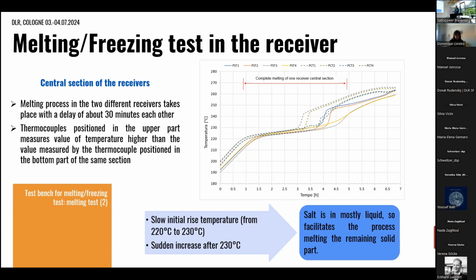Then it's possible to note that the thermocouple positioned in the upper part of the section starts to melt earlier. In fact, the thermocouple measures a higher temperature than the thermocouple positioned in the bottom part of the section. Moreover, we can see that at the beginning the temperature rises very slowly between 220 degrees and 230 degrees. After this temperature, we have a sudden increase in the value of the temperature, and it is due to the fact that most of the salt is liquid, which facilitates the melting process of the remaining solid part.